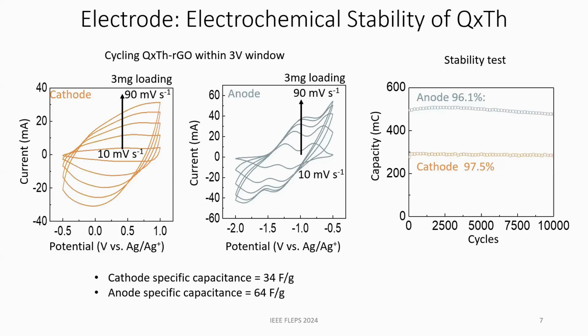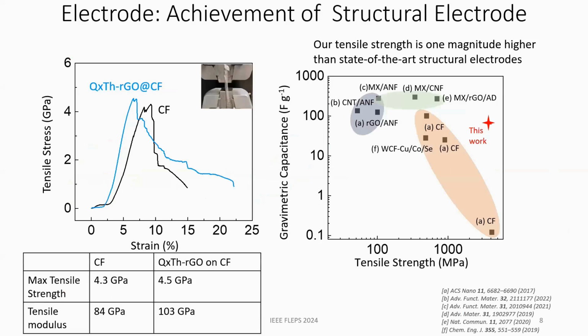Looking at the electrochemical performance, we cycled it in the cathodic and anodic region over our 3-volt window, with a high loading of 3 milligrams, and we achieved a cathode-specific capacitance of 34 farads per gram, and the anode 64 farads per gram. It was able to cycle at least 10,000 cycles and retain about 96% of its capacity. So the electropolymerization worked to adhere the electrodes firmly.